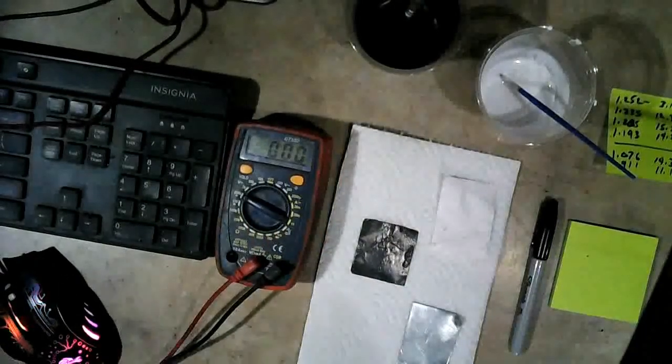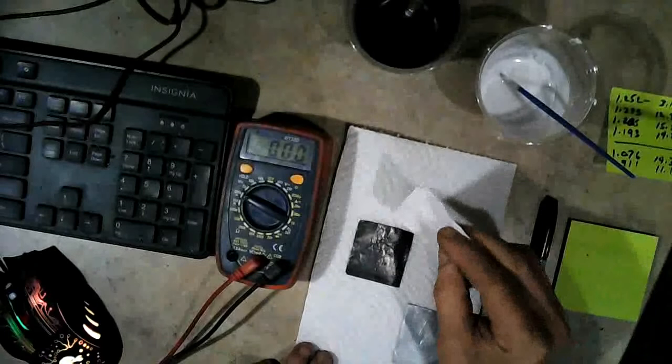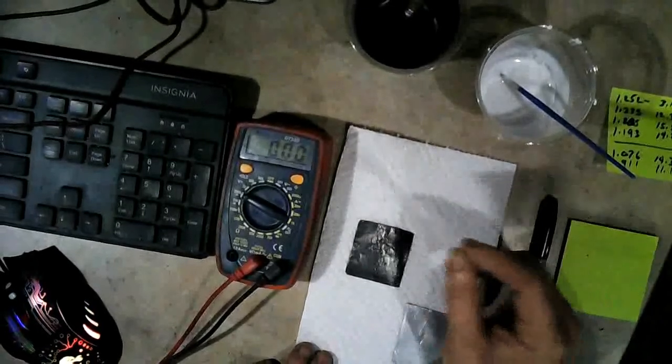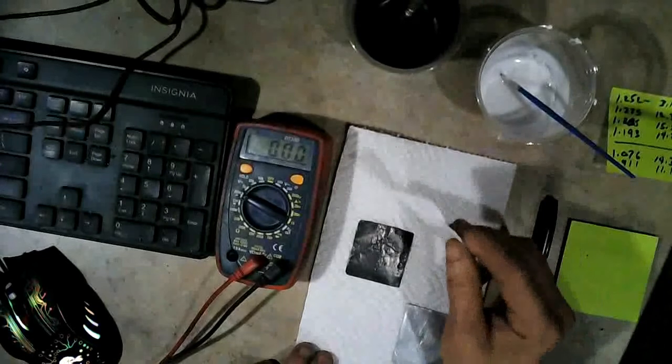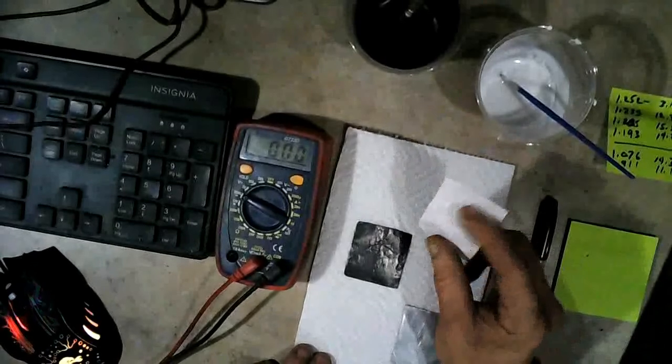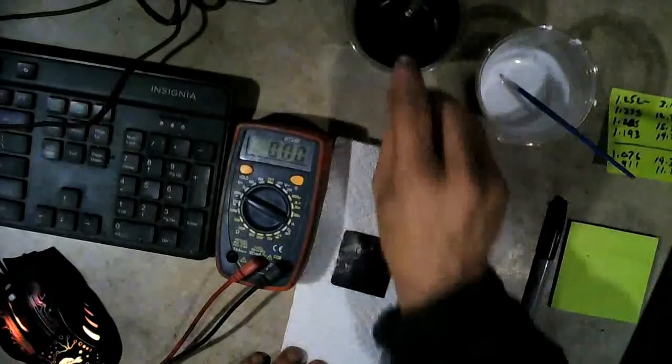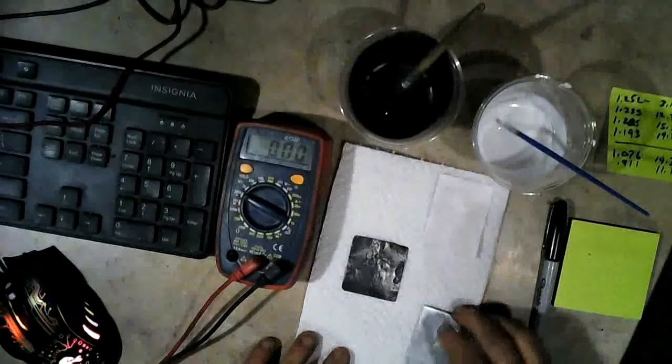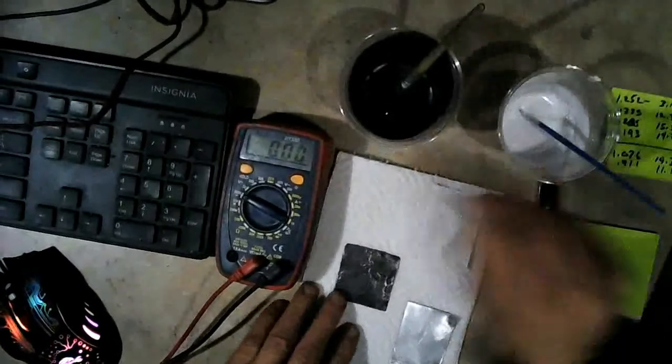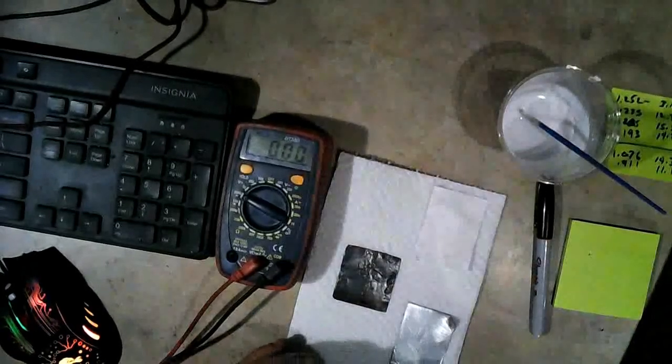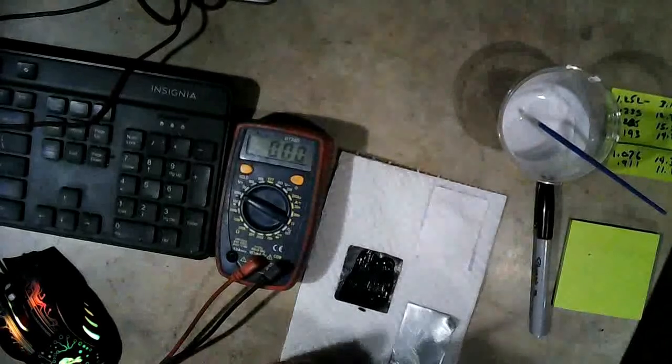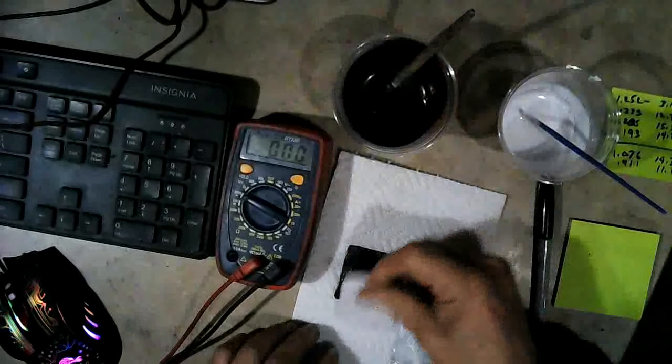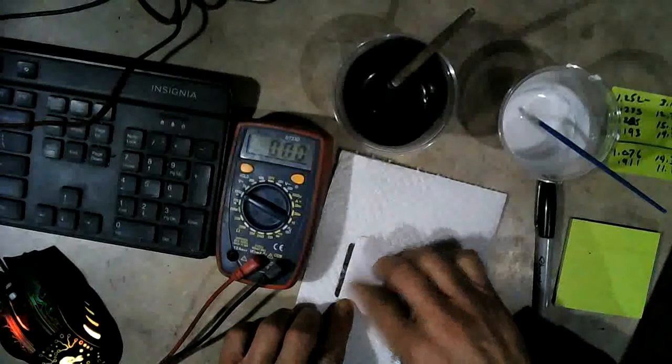Alright, I'm back and I've reset up for another experiment. What I've done here is I've took a piece of the borax paper that I've dried and I took some half white glue and half distilled water and mixed it together and then I coated both sides of the paper to completely encase the borax in the paper. And now we're going to test this like we did the other ones with just titanium dioxide and graphite and see how it performs. I suspect it might do better. So we'll put our graphite on the graph foil.